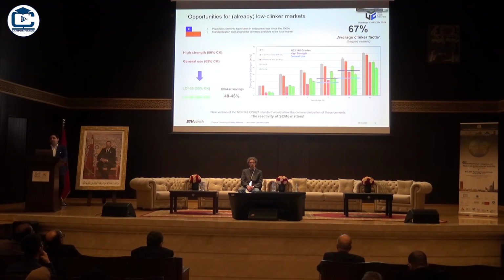And we can see that we can meet the requirement of high strength with LC335 and for general use with LC325. So basically with low clinker LC3s, we can meet exactly the same strength requirements that are in the standard, but saving about 40 to 45% more clinker than if we do it with natural pozzolans. And the difference between doing it with natural pozzolans or with a combination of calcined clay and limestone is reactivity. So this is why reactivity matters. It's not the same using inert materials or fully reactive materials as using very reactive combinations like limestone and calcined clays, because this is what opens the gate to further reductions of clinker content, retaining performance.